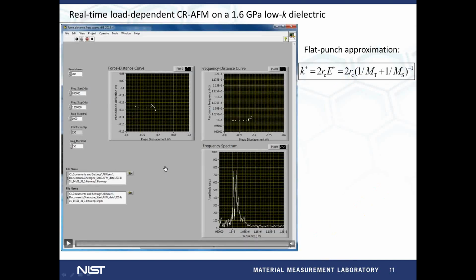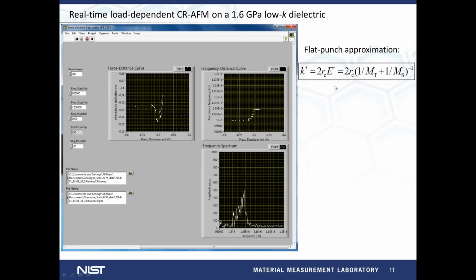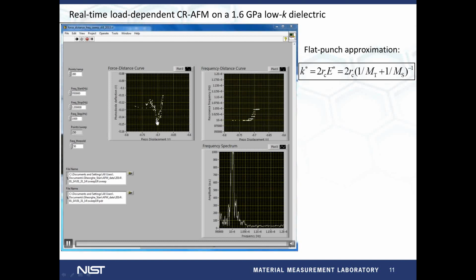Here I'll show you a LabVIEW interface where we acquire simultaneously the force distance curve measurements. It's in this window. In the lower one, it's showing the resonance frequency peak as it's shifting to higher and higher values as the tip comes into contact and pushes into contact. And here are collected the values of the contact resonance. So at full contact, we see that we have this plateau where the resonance frequency remains unchanged, which means that we have a constant contact radius, so the contact stiffness is directly related to the relative elastic modulus, and then we can extract very easily the elastic modulus of the sample from here. And we have the reverse response when the tip is coming out of contact. Here the frequency spectrum is showing again the free resonance, the second eigenmode of the cantilever, around 1 megahertz.